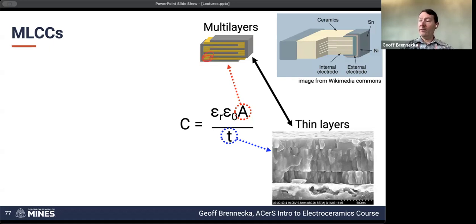And we haven't talked in great detail about field enhancements, but anytime you have a sharp point, anytime you have a contrast in dielectric constant in permittivity, there's going to be an enhancement in the electric field. And so a lot of times failure will occur anytime you have these kind of edges and boundaries, because that's where the field is going to be concentrated. So those margins end up being very important because they're a region where a lot of the field is concentrated, but you want those regions also as small as possible to be able to maximize the energy that you can store.